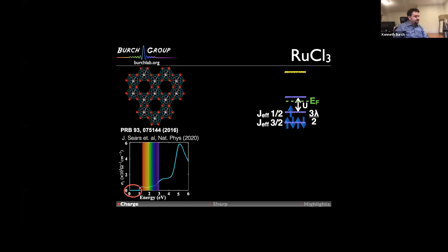Because of the narrow bands, you find very little absorption in the visible. The key point is that the work function, as I said earlier, is 6.1 EV, and the Fermi level is close to this conduction band, but again, this conduction band is very narrow. This comes from the strong electronegativity of both ruthenium and chlorine and this relativistic Mott-insulating state. The key point is that if you then compare that with monolayer graphene, the graphene has a work function of 4.6 EV, and so you would expect an enormous amount of charge transfer going from graphene into ruthenium chloride. There's nothing special about monolayer graphene in that sense. Bilayer graphene has roughly the same work function, but now you have a higher density of states. So even for the same change in Fermi level, you'll get many more carriers doped into the bilayer.